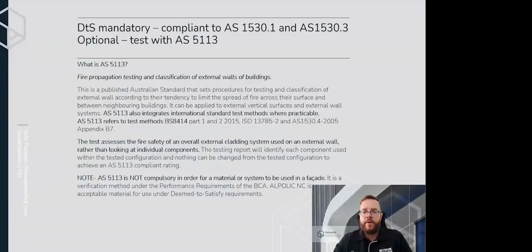At the core of this test is whether the products will propagate the spread of fire separate to the ignition point. For example, the facade panel might not spread fire, but can open the cavity, exposing the insulation which could then itself catch fire and spread internally up the cavity. By using this test method, we can see what products work well with each other and what products don't. This test also incorporates a wing wall as opposed to other tests, which we'll go over now. I will like to point out again, just down that bottom, 5113 is not compulsory in order for material or system to be used in a facade, meaning that if you have deemed to satisfy compliance, that is the way forward for your product. 5113 is always good to do as an extra though.